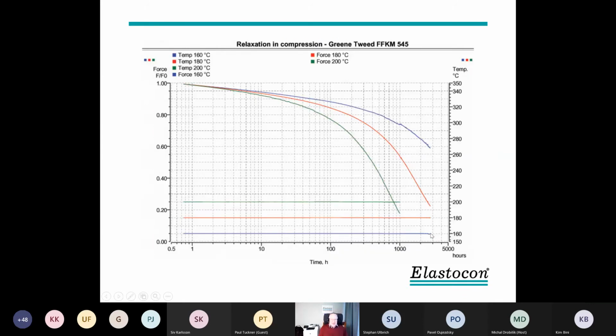Here we have a material we tested a long time ago. It's a fluororubber, which is one, I think it's the most expensive rubber we have. We tested quite a long time at 3 temperatures, 160, 180, 200 Celsius. The force graph looks like this. The lowest temperature of 160 didn't reach more than 40% relaxation.